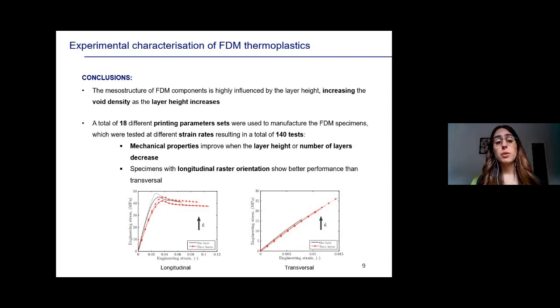Then we carried out different tensile tests. As I said, we used 18 different combinations of printing parameter sets. We tested these specimens at 2 strain rates, resulting in a total of 140 tests.